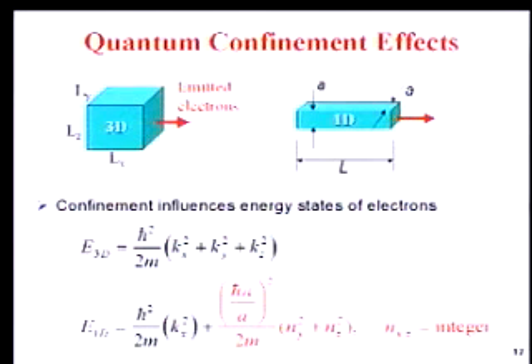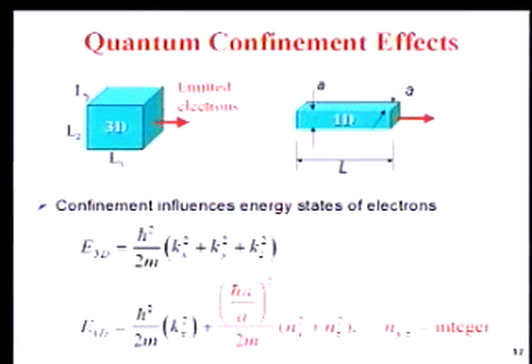What can happen in this case is, when I heat up this material in the 3D case, it's kind of like adding energy to a balloon. Force times distance, I push the balloon in, and it spreads out in all three directions. In the case of the quantum wire, it's like a straw. I squeeze the straw, and almost all the energy goes up. And if I align this quantum wire in the direction that I'd like to see emission occur, then we might expect that the thermionic emission performance would change.